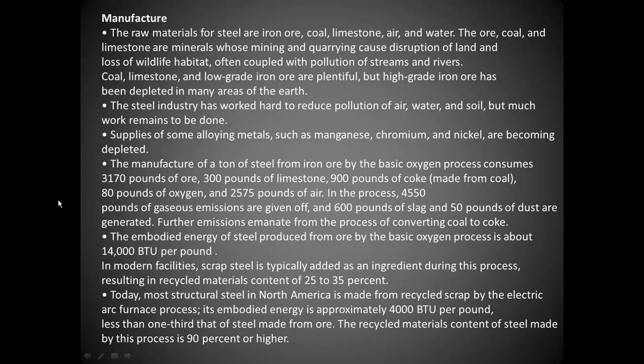The manufacturing of steel, from a sustainability standpoint, and I won't go through all of this material because it's fairly technical, but if we look at the material it requires to create 1 ton of steel: 3,170 pounds of ore, 300 pounds of limestone, 900 pounds of coke, which is made from coal, 80 pounds of oxygen, and 2,575 pounds of air.